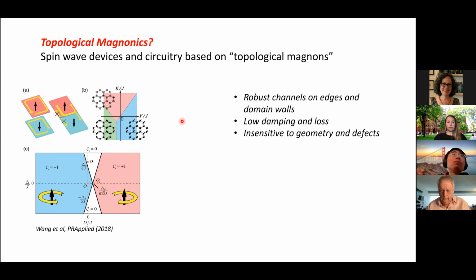But there are other cases where the magnon system can have non-trivial topological properties compared to electrons. One of them is the surface magnetostatic wave. For electronic systems, when you have a surface state, it typically sits between two bulk bands, connecting them - that's the typical picture of an edge state. But in the case of magnon systems, you can see cases where the magnon has energy higher than all the bulk bands, so on top of all the bulk bands you can have some non-trivial magnon bands.